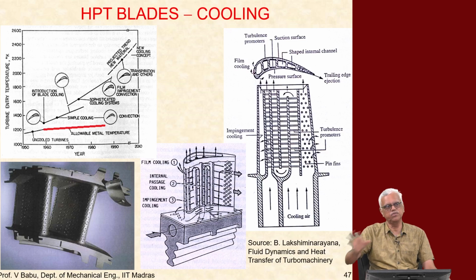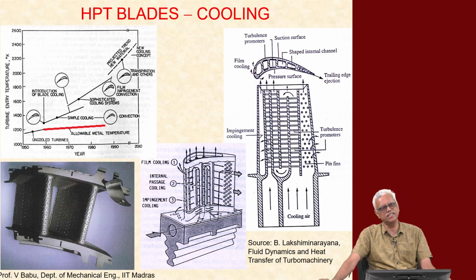So, you can keep a flow going, and the film also can be maintained, otherwise the film will be disrupted or film may not even form. So, you need high pressure air to go through these small passages. And when I say cool air, that air itself is at a temperature of about 500 degrees Celsius. That is cool compared to 1400 degrees Celsius. That still provides a 900 degrees Celsius temperature difference. You need the high pressure air. So, you draw the air from the high pressure compressor and then use it for blade cooling purposes.